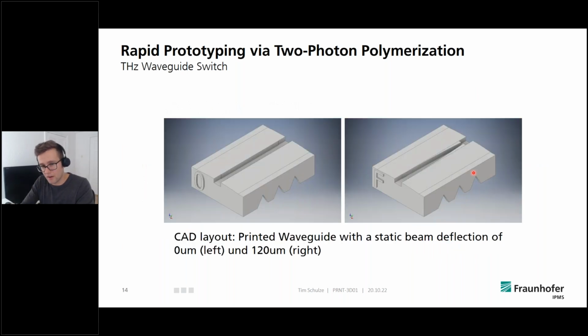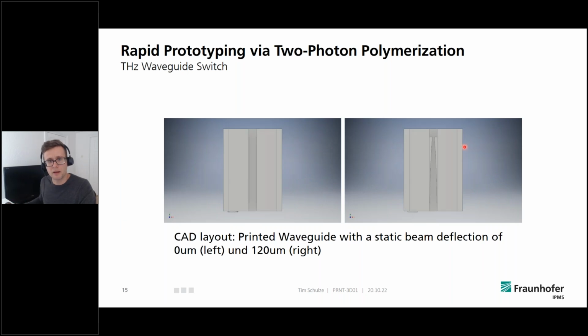The first time I did this with static structures, so not real bending capability, but I did a parameter sweep over different components. For instance, here you see the CAD depiction of my waveguide with a bending beam inside with zero deflection. And then I did a parameter sweep over different other components where the deflection is a little bit higher. For instance, here it's 120 micrometers. And here I think it's a little bit better to see. So here zero deflection, and here bending beams with a 120 micrometer deflection.